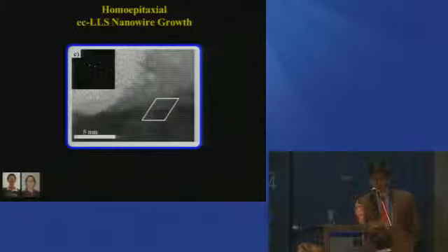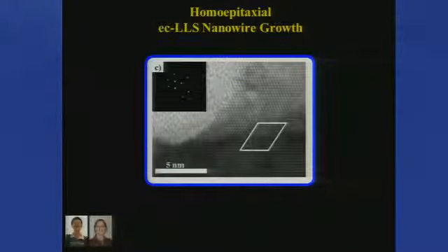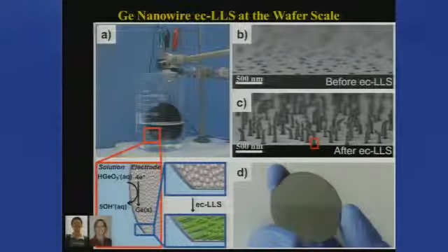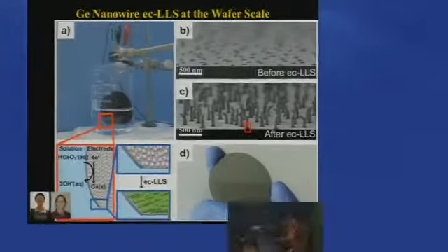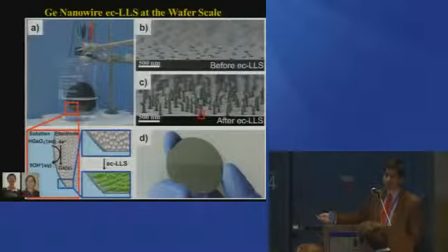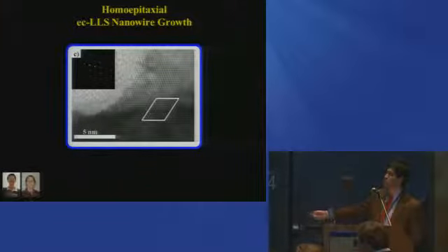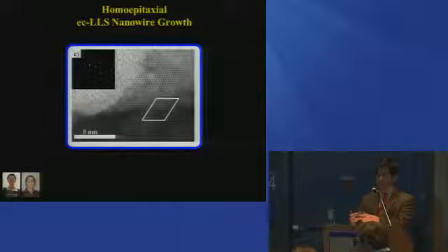When we talk about making nanowires in this case, these are not, for lack of a better term, crappy nanowires. These are really pretty good. The nanowires that you see in this experiment, first off, are all straight. Straight indicates that there is some level of order, and that order comes from the fact that these are all single crystals with epitaxy with the substrate. That wafer substrate is a big piece of a germanium crystal, and we are electrochemically growing extensions of that crystal. And you can see that directly here.